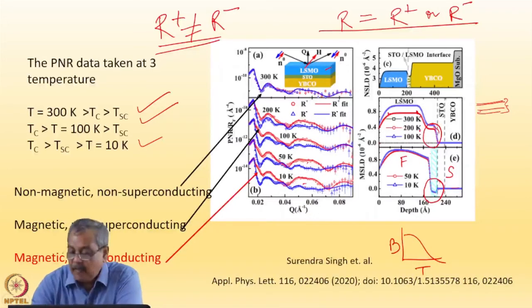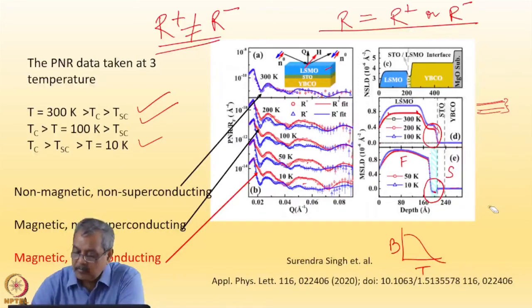When I have gone superconducting, then at the interface, you can see this magnetic moment density drop to zero, drastically drop to zero, or close to zero, marginally negative.